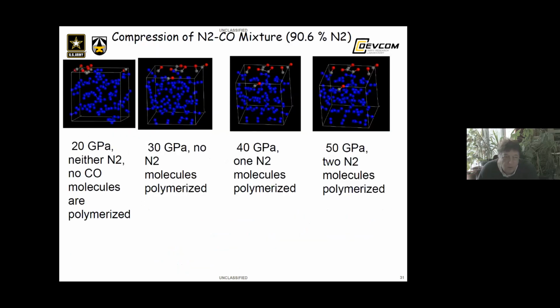Let us start from a small amount of CO in molecular delta phase, almost pure N2 crystal, and start computationally isotropically compressing it. At 20 GPa no polymerization, 30 GPa no polymerization, only at 40 GPa one polymeric molecule, and two molecules at 50 GPa.